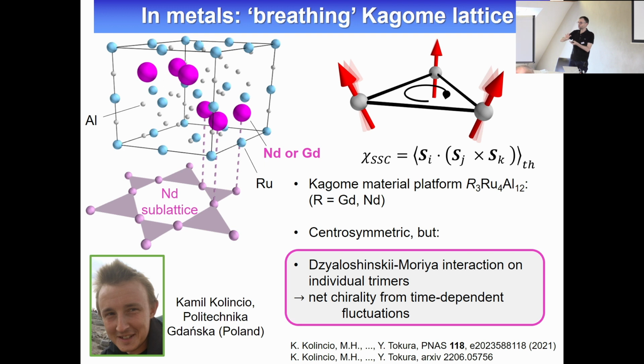So we kind of destroy the long-range order by thermal fluctuations, but we still observe a very large kind of Hall response of conduction electrons. So the nice thing about metallic systems is that the spin fluctuations, of course, are on the kind of megahertz or gigahertz frequency scale, but the conduction electrons typically have a much higher or faster kind of response time. So you can assume that at every instant, the magnetic texture is static, and the electron just feels the homogeneous emergent magnetic field at that moment, and then you just do a time average. So the separation of timescales for the conducting systems is very convenient.